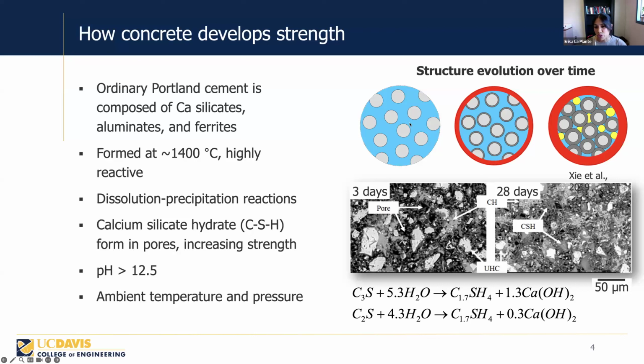And what happens over time is the cement grains dissolve. That changes the composition of the pore solution, leading to supersaturation with respect to hydration products. And then you have the precipitation of these hydration products that then fill in the pores. The important hydration product here is what we call CSH, or calcium silicate hydrate, and that is what's causing the increase in strength over time.